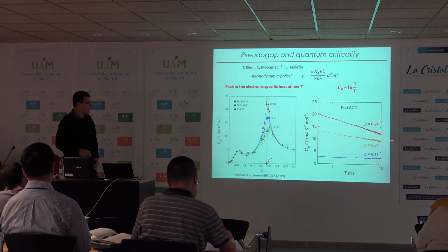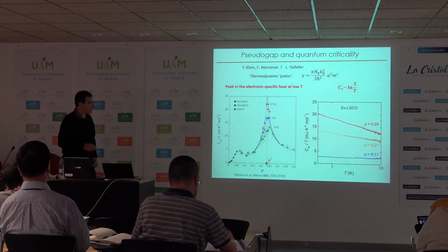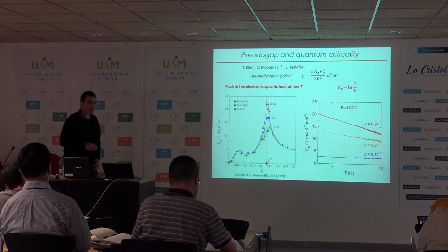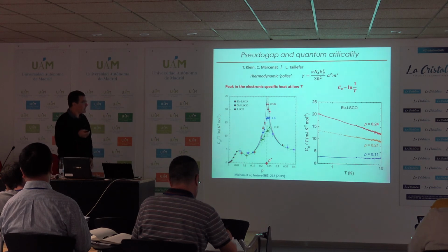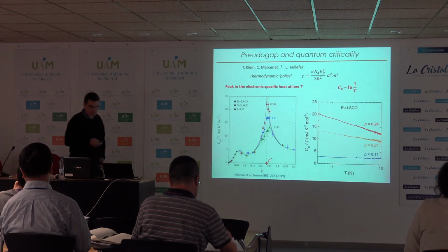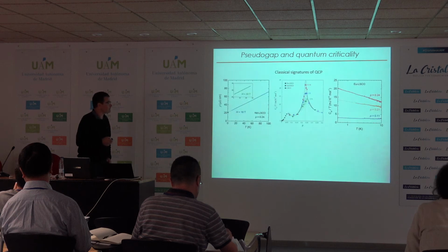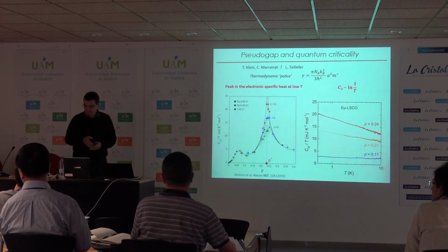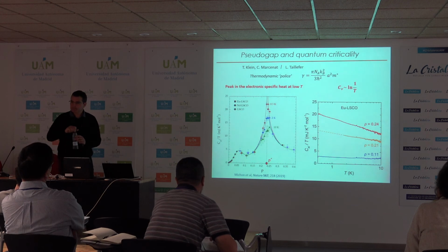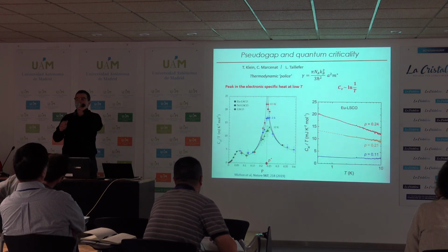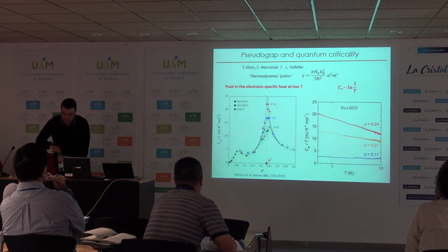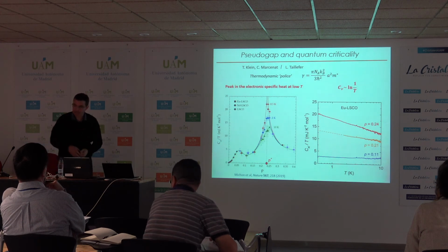You see that at the critical point of the pseudogap, the specific heat behaves as log 1/T, as again you expect for a quantum critical point. Sorry, one question. This is just the electronic specific heat, even at 10 Kelvin? Yeah. So phonons have been subtracted. Phonon and Schottky anomaly. And Schottky.